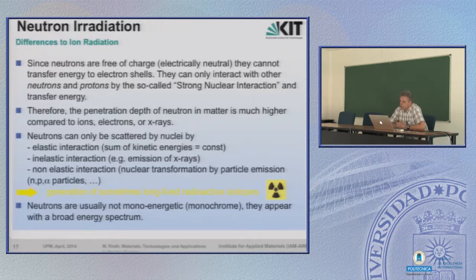And in these non-elastic interactions, nuclear transformation by particle emission takes place, and this is what in the end leads to radioactive isotopes. If you irradiate matter with ions, then there is no activation. The result is a non-radioactive material, but if you irradiate matter with neutrons, then in almost all cases you end up with radioactive isotopes. That's a big difference.